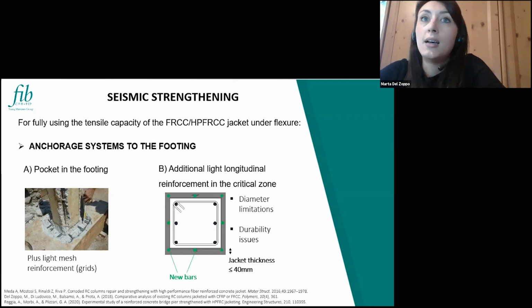The other option is to add additional new light longitudinal reinforcement just in the critical zone of the member to guarantee the connection between the footing and the jacket. But in this case, of course, we need to consider that the thickness of the jacket is really small. So to avoid corrosion issues, we need to select a material and also a diameter for these bars that should be able to avoid durability problems and the corrosion of the bars. In any case, of course, when we increase the flexural capacity of the members, we also need to ensure that the correct hierarchy between the shear and the bending is respected. Otherwise, we are creating a new problem, creating a shear critical member. So when we connect the jacket with the foundation, we need to pay attention to the shear capacity too.